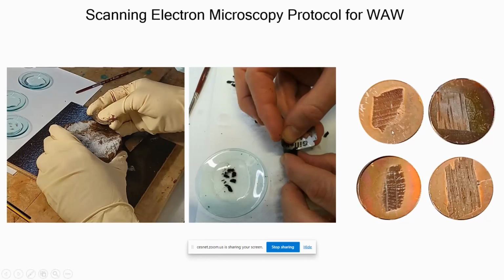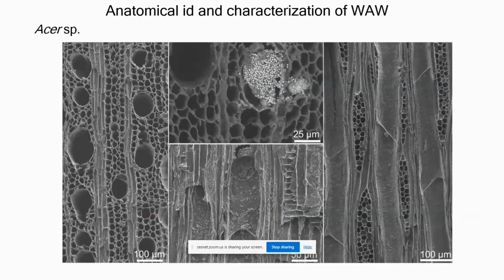They are glued on the stub with albumin, and then inserted in the oven for 15 minutes at 70 degrees, in a way that the albumin becomes like a glue, and the section stays on the stubs without shrinking. So in this way, we can observe the wood under the scanning electron microscope, and you see that we can get very high magnification. We can also have a large image for the identification.